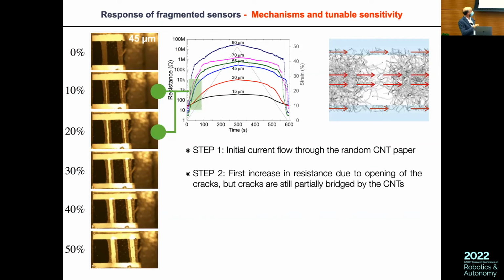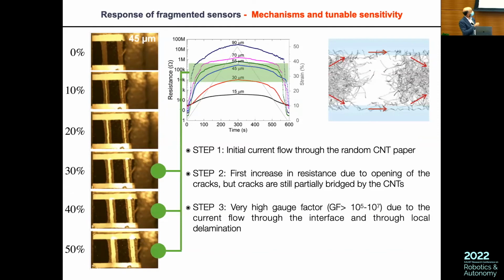And when you start to increase in the second step here, the resistance starts to increase very quickly, and this is due to the fact that you are breaking progressively the bridge in the CNT paper, and you start to have conduction through the interface on the top. And what really gives the high piezoresistivity, that means the high resistance here, is when you have separation of the fragment, but you have conduction through the delaminated interface. You can show this. In fact, the delamination is what makes things work in this kind of system.